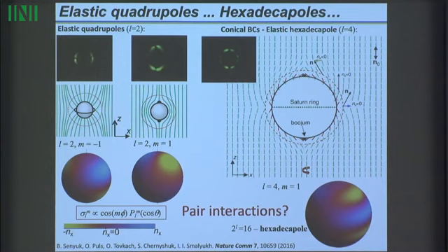And we already know from Micha's lecture that this is because the Frank free energy minimization gives us the Euler-Lagrange equation, which is of Laplace's type, and then expansion of the solution into multipole series allows us to bring about these analogies.